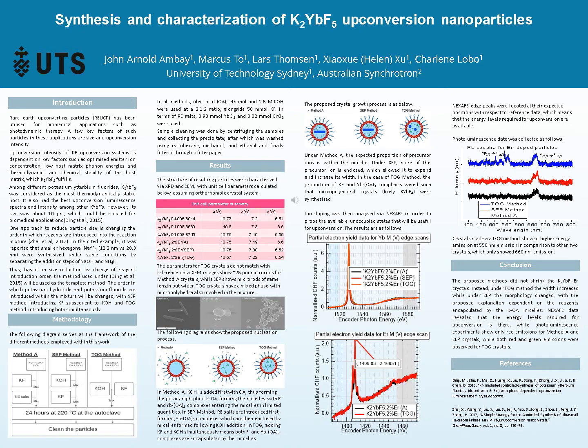And according to our photoluminescence results, we see that we get green and red emissions for the crystals made under the together solutions method, whilst we only get red emissions for those made under method A, the original method, and the separate solutions method.